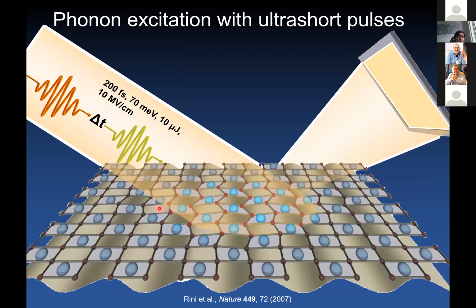And the way we try to pursue this type of experiments is by coupling short pulses of laser light in resonance with phonon modes. So we want to perform the most gentle perturbation we can to the system while still being effective. And so the idea is to create pulses of light in the mid-infrared range that are tuned in resonance with phonon modes of the material, displace atoms out of their equilibrium position to a large extent, and cause a rearrangement of the electronic degrees of freedom in the system.